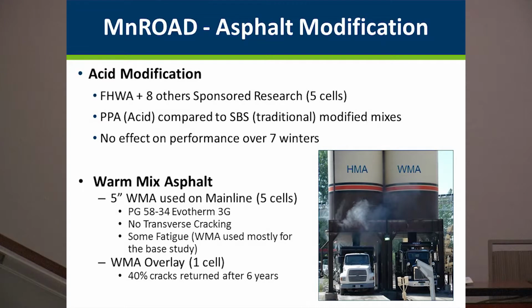We did some other things with Federal Highway and other supporters, but we had some questions about acid modified. Is that as good as using traditional SBS? We built three test sections, one with PPA acid, one with PPA and SBS, and another one with SBS. Over the years that we've looked at it, and we used a minus 34 oil, they all performed perfectly. I know there's been some questions nationally about that, and I'm not sure how much acid modified is a big deal now or not, but we saw no difference in the performance of those for that kind of modification.